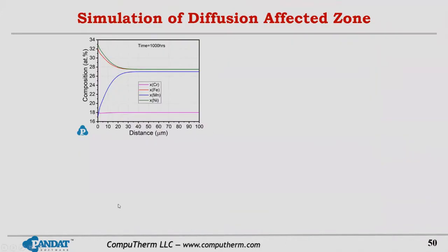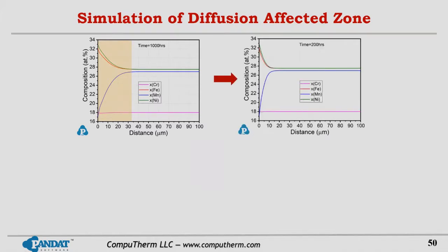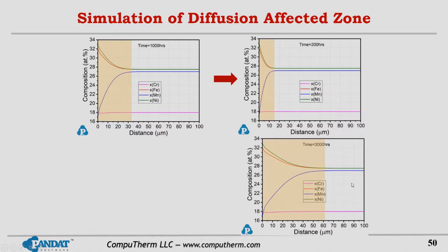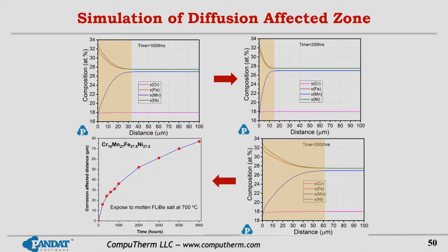And from diffusion simulation, basically we can use available experimental data to calibrate the flux and so on information, and then we can simulate the diffusion effect layer. So this first plot is for 1000 hours, and the second one is for 200 hours. Then we can project it to even higher numbers of hours, like 3,000 hours, and so on.